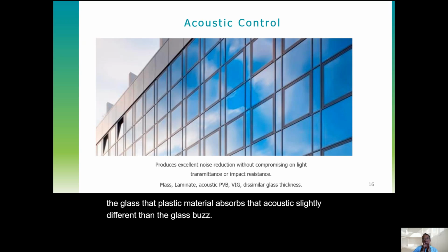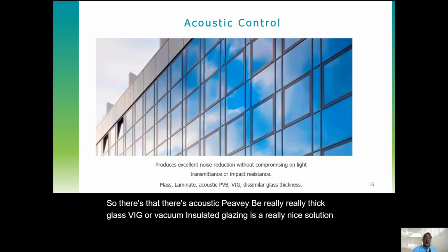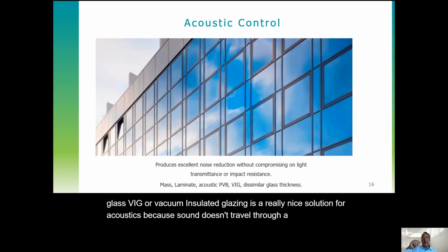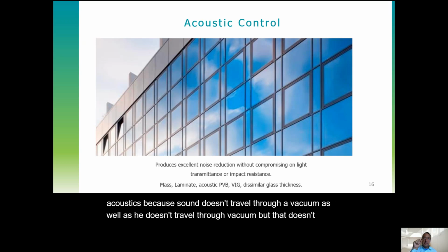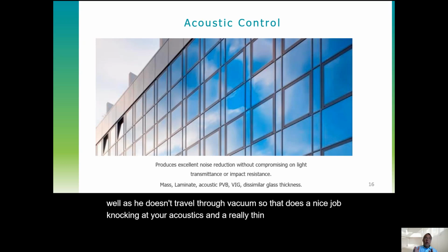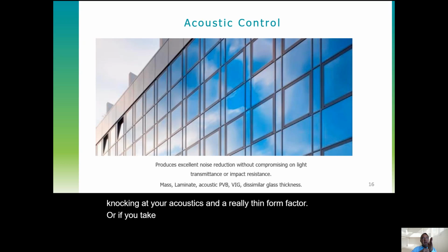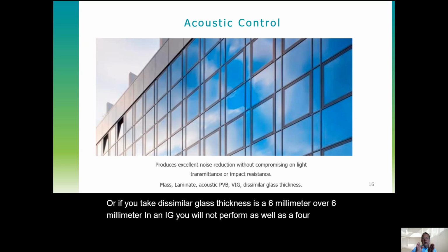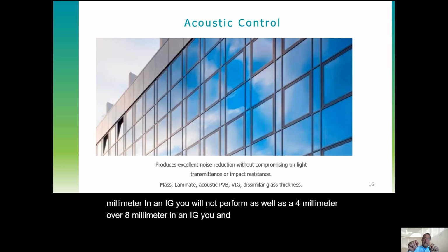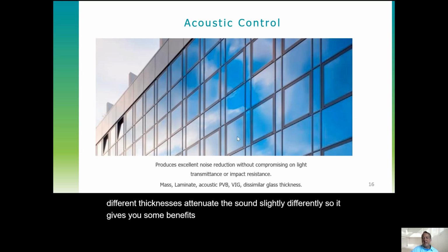So there's acoustic PVB, and really, really thick glass. VIG, or vacuum insulated glazing, is a really nice solution for acoustics because sound doesn't travel through a vacuum, just as heat doesn't travel through a vacuum. So that does a nice job knocking out your acoustics in a really thin form factor. Or if you take dissimilar glass thicknesses, a 6 millimeter over 6 millimeter in an IGU will not perform as well as a 4 millimeter over 8 millimeter in an IGU. That's just because those 2 different thicknesses attenuate the sound slightly differently, so it gives you some benefits. But generally, acoustic solutions have one of those kinds of combinations.